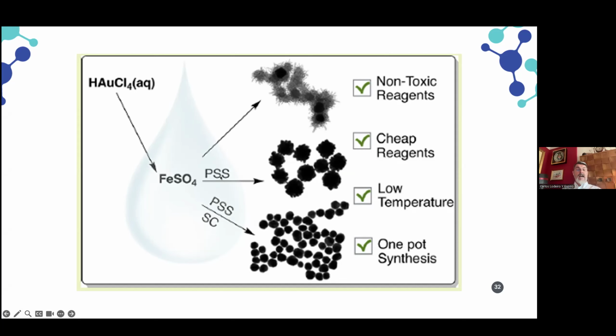If we use an organic stabilizer like PSS, we can obtain nanowires, and if we also add citric acid at the same time, we can change these nanowires into nanoparticles. So in the same reaction, using non-toxic, very cheap reagents, working at very low temperatures, we can produce three different nanomaterials in one synthesis. The use of polystyrene sulfonate as a stabilizer was very useful in order to create the anisotropy in the nanowires. The problem was later, because this PSS molecule is not safe and has some toxicity that reduces the applications we can use it for.